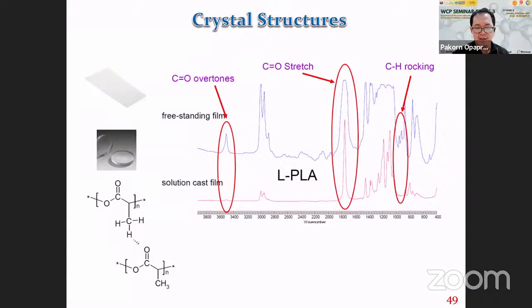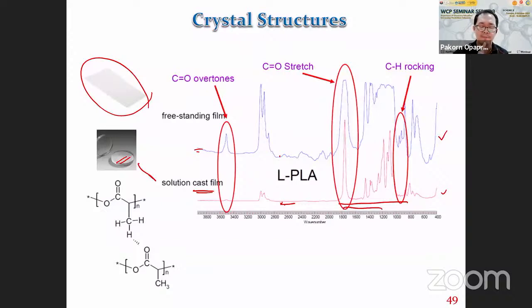And this is also quite unique. These are 2 spectra that come from the same materials. But the top one here comes from a freestanding film, and the second one comes from a solution cast film, like on a KBr window. The bottom one here, the sample is very thin. When the sample is very thin, you can see the spectrum is very good, high quality, suitable for quantitative analysis. But there are some peaks that are quite small.